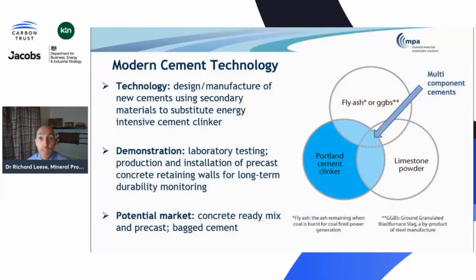The Venn diagram illustrates the concept for the new cements in this project. In the UK, cement formulations currently consist of 2 main components. That's clinker, the energy-intensive product from a rotary cement kiln, and either fly ash or GGBS or limestone powder. In this project, MPA and industry experts developed 22 new multi-component cement compositions based on 3 main components. That's clinker plus limestone plus fly ash or GGBS. Using less clinker provides an opportunity to improve energy efficiency and to reduce embodied carbon.